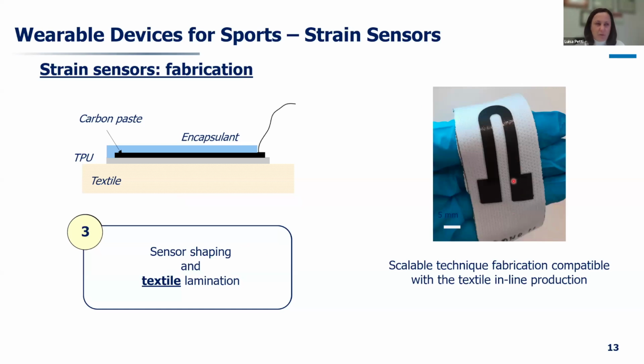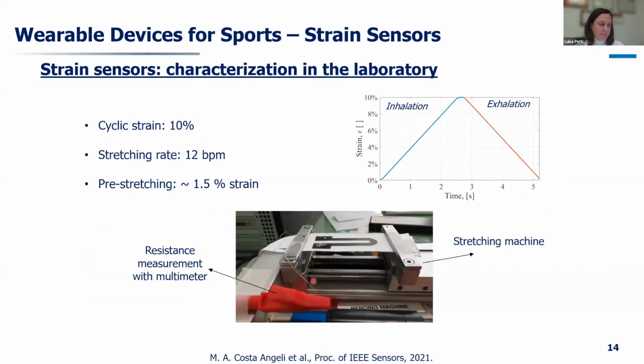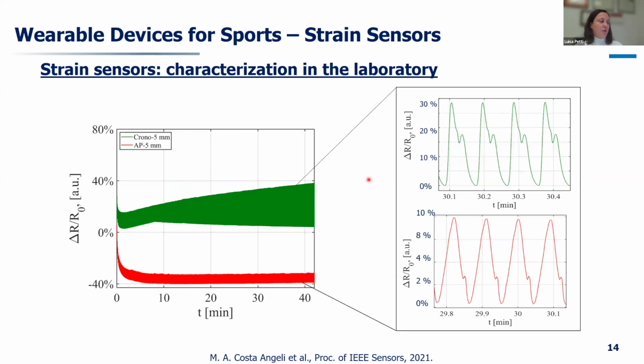This is how the first prototypes look. Now this is integrated into a t-shirt, but with the U shape, which clearly is better in terms of stretching. And everything, as visible, screen printed. Everything was first characterized in the lab as usual, looking at a similar pattern of what we have in terms of inhalation and exhalation, with the same stretching rate, and measuring everything in a customized stretching machine that we have in our lab. So we tested these two textiles, the Chrono and Asteria Pesante, if I remember the name well, and those are the enlargements of the patterns of the two different sensors.